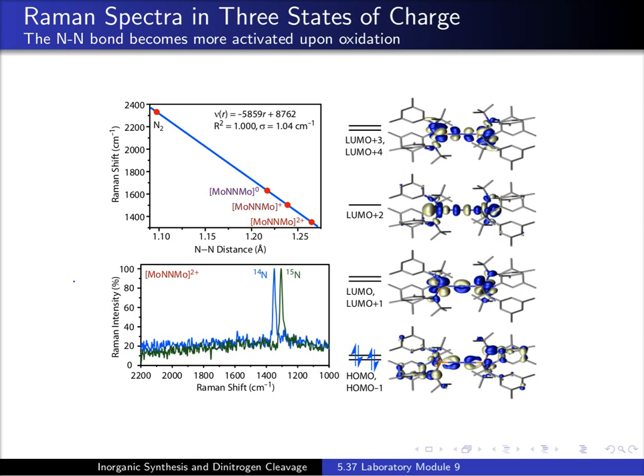And that same graduate student was able to characterize this bridging N2 complex in three states of charge. He was able to isolate it as the neutral species that we were just looking at, that you'll be working with. The neutral species, as we mentioned, has an NN bond distance of just a little longer than 1.2 angstroms, a tenth of an angstrom longer than in free dinitrogen.